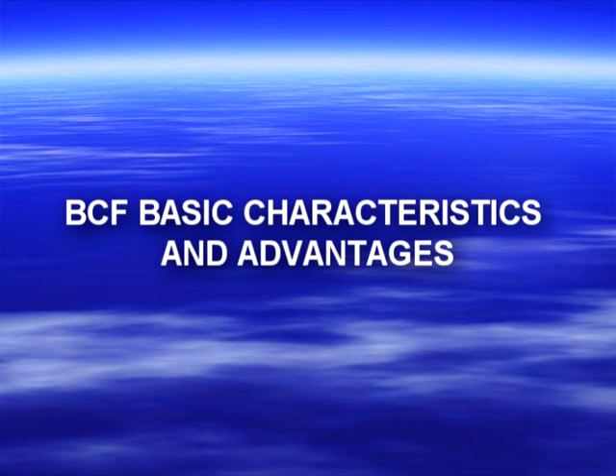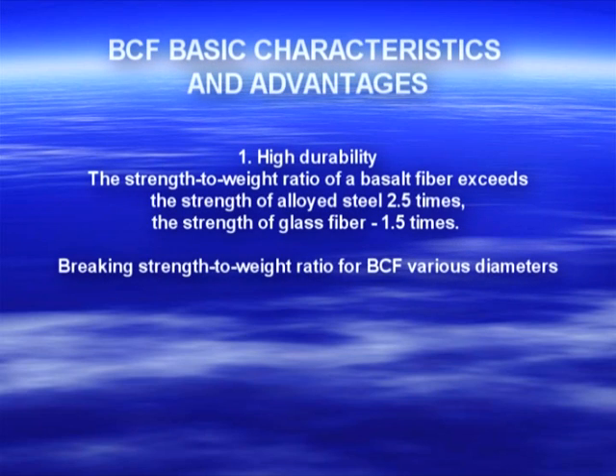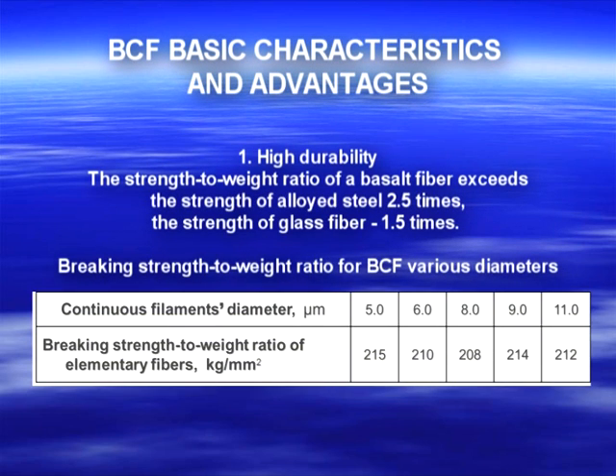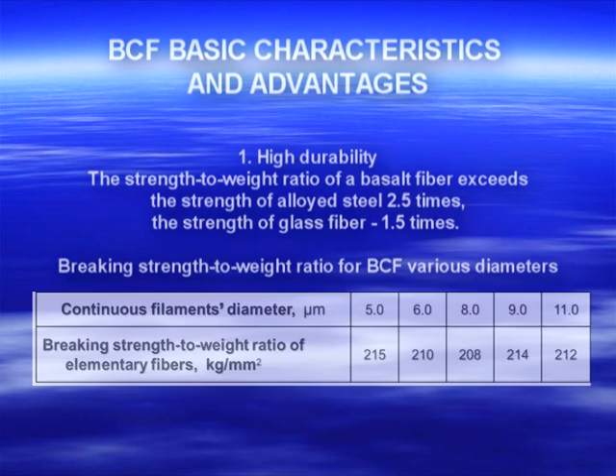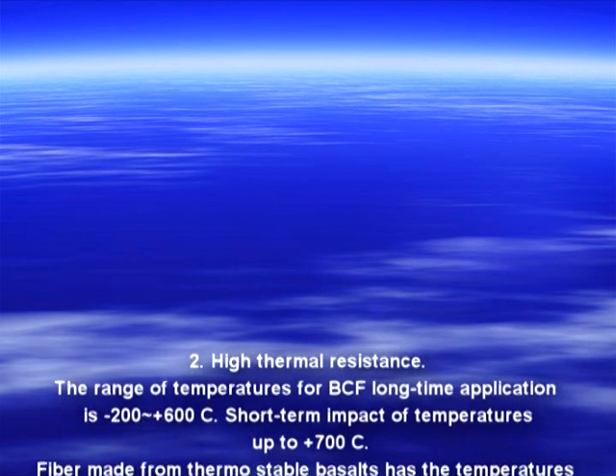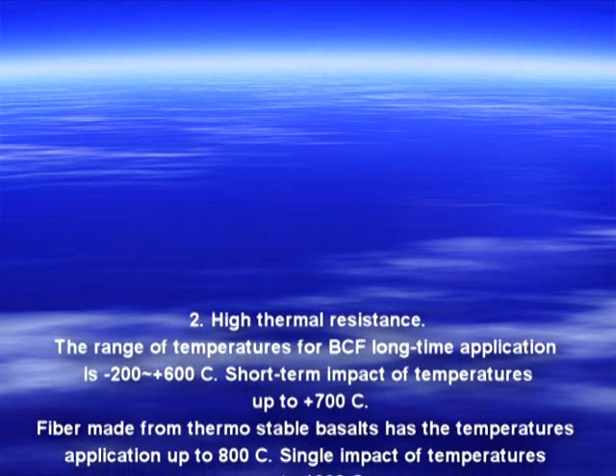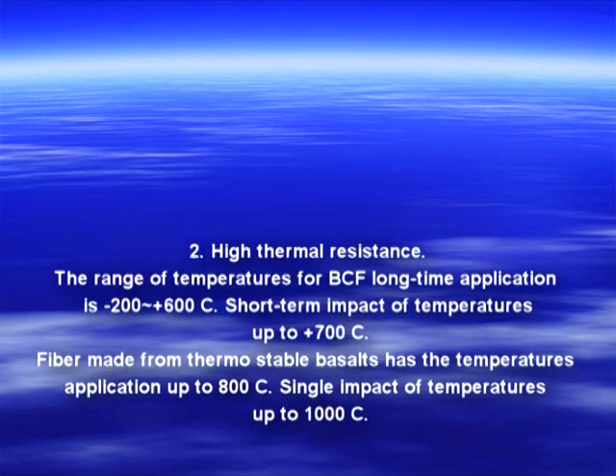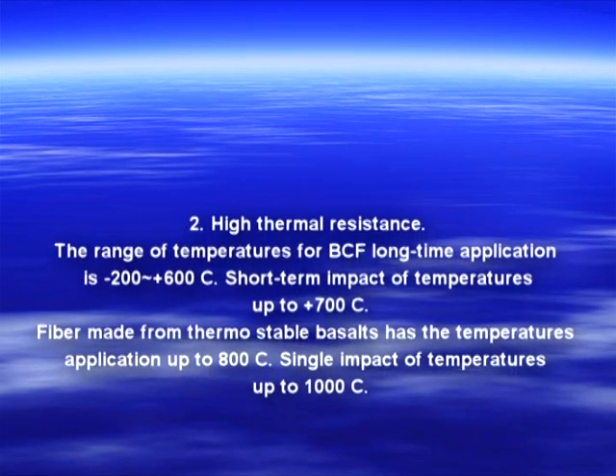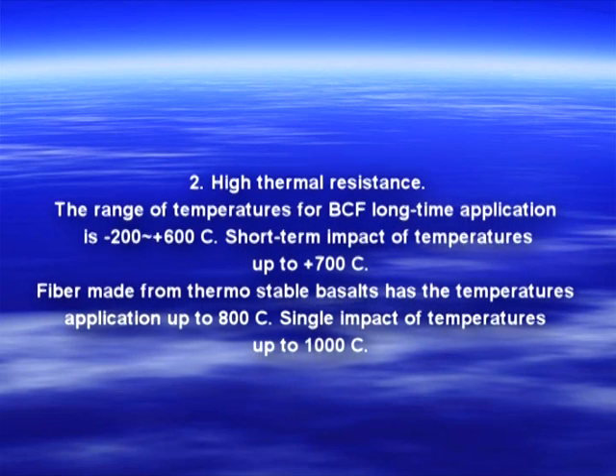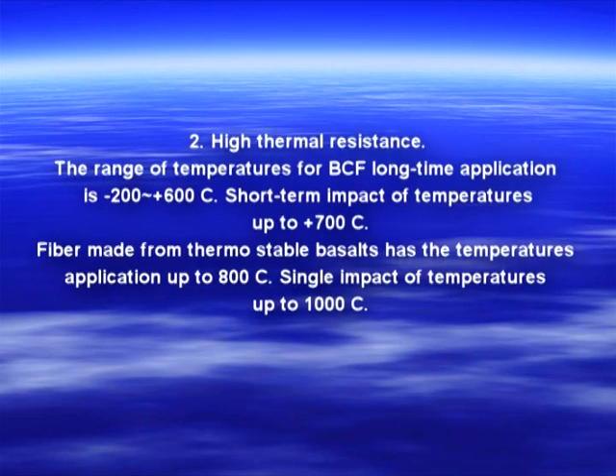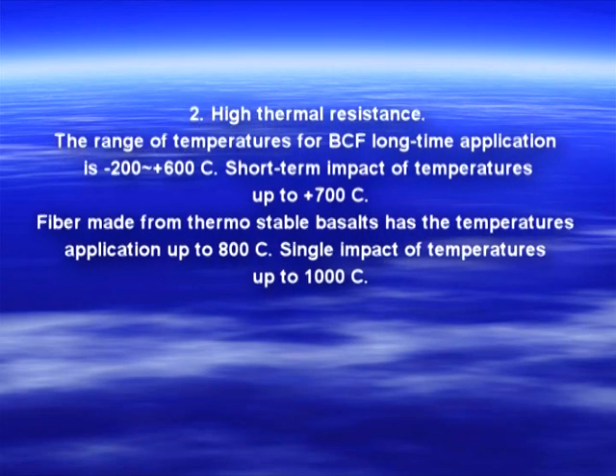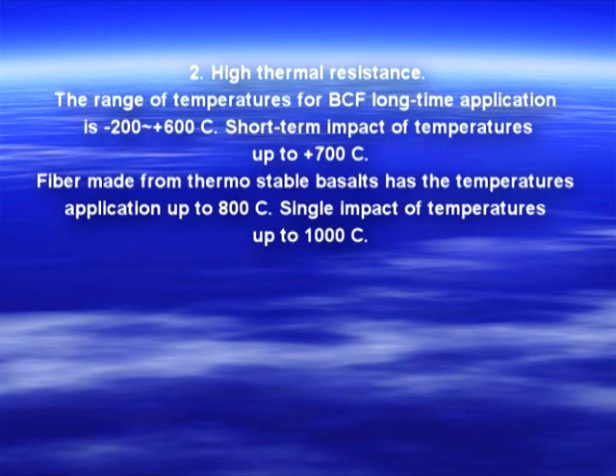BCF basic characteristics and advantages. High durability: the strength-to-weight ratio of basalt fiber exceeds that of alloyed steel by 2.5 times and glass fiber by 1.5 times. High thermal resistance: BCF can be used long-term from −200°C to +600°C, with short-term impact up to 700°C, thermostable basalt fibers up to 800°C, and single impact up to 1000°C.